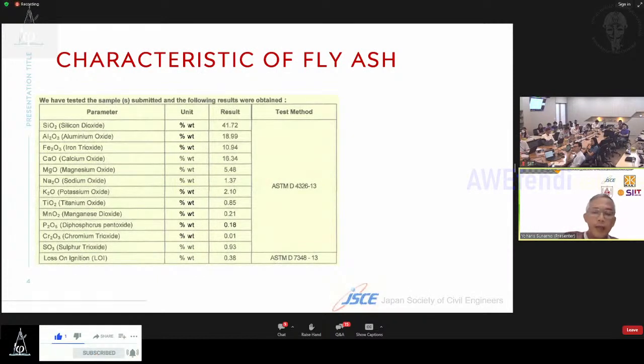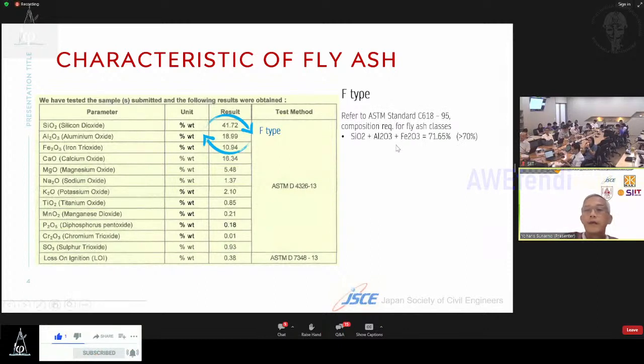And these are the characteristics of fly ash. Based on the following fly ash sample characterization from test data, there are several important mineral contents in fly ash that indicate the type or class of fly ash. From this fly ash test, we can see that this fly ash is Class F, because the total of silicon dioxide, aluminum oxide and iron trioxide is more than 70%. This is the class of fly ash that we use for our factory in Makassar.